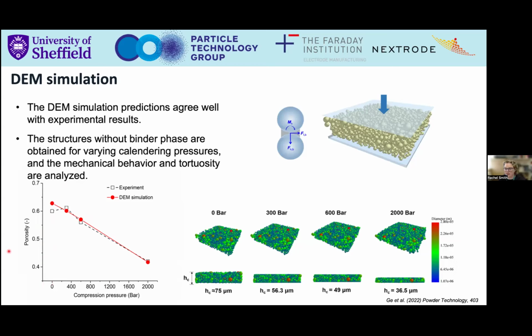Now, of course, we have to do some calibration here, right? Some of the parameters in the DEM simulation are not well known. So we have to do calibration here. But what we find is that if we can then keep those parameters constant across all the different compaction pressures, and this is the result here basically, we're quite confident now that our model is giving us a good result.